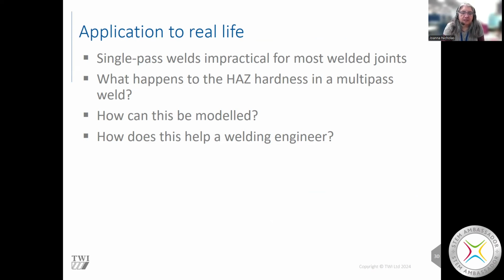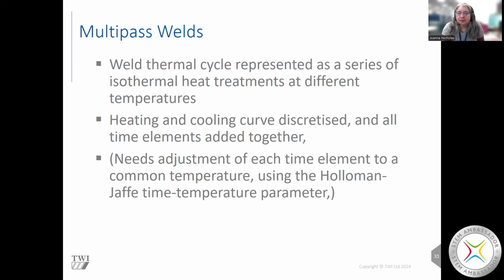What happens in the heat affected zone in a multi-pass weld? Can we model it? And how does it help the welding engineer? Well, we can consider the weld thermal cycle as a series of heat treatments, and we can kind of separate out the heating and cooling curve as kind of little segments that are then added together. And we use this Holloman-Jaffe time temperature parameter, which I spoke about when we talked about post-weld heat treatment earlier.